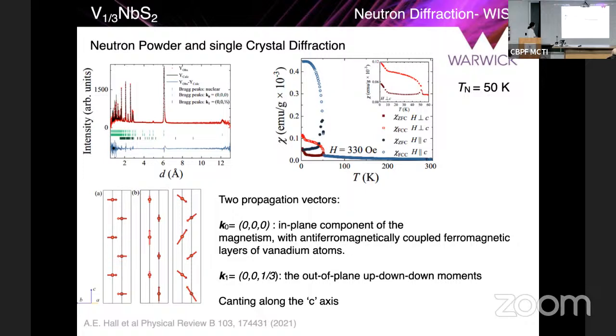So what we see is two propagation vectors, one which is the in-plane component of the magnetism, with the antiferromagnetically coupled layers of vanadium atoms, which are ferromagnetically coupled to each other. And then another propagation vector, which is the out-of-plane up and down moments. And this is the resulting structure that we propose as a combination of these two, which is canting along the C-axis. Okay. This does not exhibit a chiral soliton lattice.